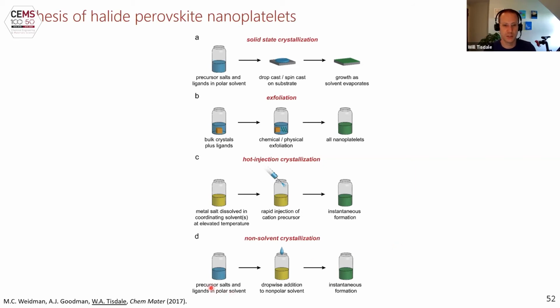It's quite simple. We take all of the salts, the lead halide material, the perovskite material, all of the ions that end up in the final structure. We dissolve them in a polar solvent, we add a little surfactant, and then we drop that into a non-polar solvent. And you'll get crystallization at room temperature of two-dimensional sheets stabilized by the surfactant layers on the surface.